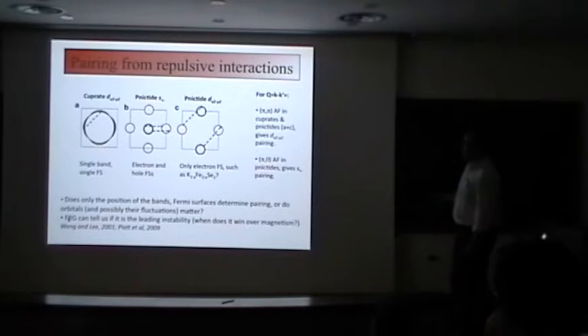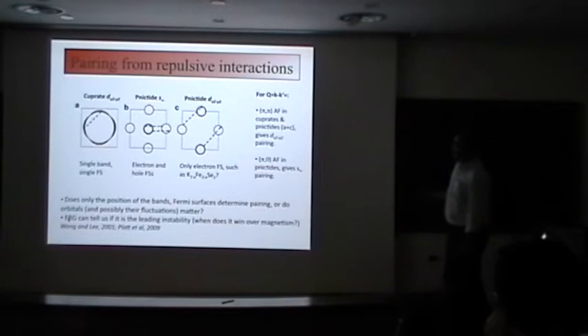And if this orbital goes away, so that's the one sitting at the gamma pocket, then the only way that you can get pairing from a repulsive model is to have the gap change sign going around on the electron Fermi surfaces. So that would be a dx squared minus y squared pair state.